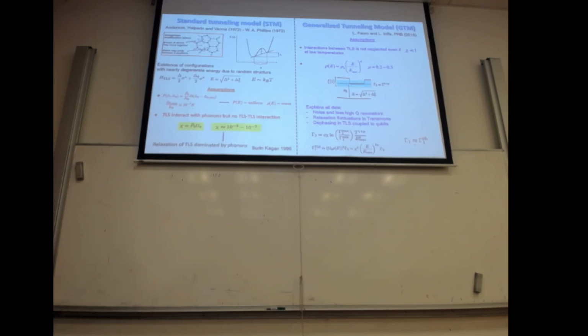So we are slowly coming to the conclusion, a lot of information. One of the main things is that the standard tunneling model does not apply to our decoherence, and we understood why. We are dealing with surfaces that have spins, incoherent fluctuators, and this affects greatly how the dephasing of the TLS is affected, as we proved nicely with this experiment in resonators. But from this theory of the interaction with the fluctuators, you don't see an effect in the gamma 1 of the qubit, because the kind of relaxation that you expect from a fluctuator is basically irrelevant.